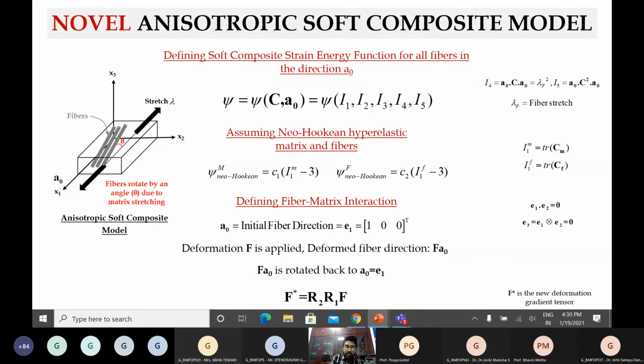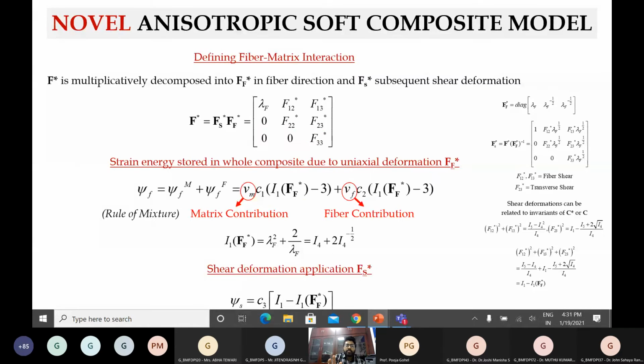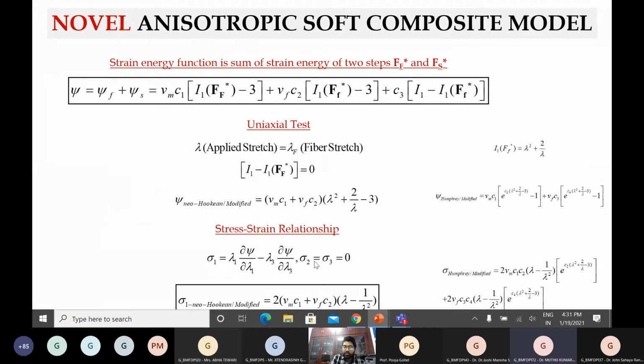So this model specifically is much more complex. Here we have fibers within a softer matrix, and whenever there is a pull or stretch to the matrix, the fibers rotate by a certain angle. We use different rotational tensors to bring this back. I'll just quickly highlight the steps, not going into the mathematics part of it. There is something called a multiplicative decomposition of fiber along the fiber and the shear deformation in the other direction. So overall, we come out with a strain energy function where we also include a matrix and fiber volume fraction contribution. And then we finally club this all together. And finally, what we get through a uniaxial test is a model like this, which is your strain energy function. And the stress strain relationship comes out to be like this.